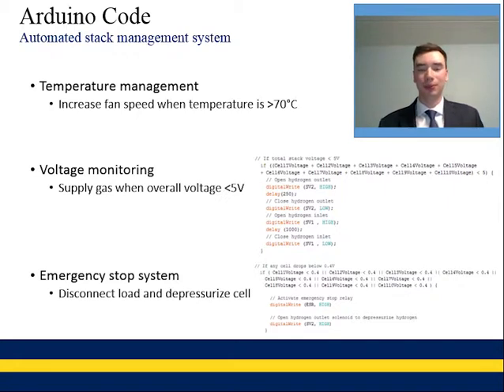So some sub-programs that we have in here: we have temperature management, where if the cells get above 70 degrees Celsius, we're going to increase the pulse width modulation duty cycle to 100%. It's normally going to be around 50% to keep overall power consumption down. But if the temperature gets too high, we're going to have to increase the fan speed to provide more cooling. We also have a voltage monitoring system: when the hydrogen gas gets used up, the overall voltage is going to drop across all the cells. So when it gets below our set 5 volts, we're going to depressurize the cells, which is going to let out mainly nitrogen because the hydrogen is going to be used up. And then we're going to let more hydrogen gas in and repressurize the cell and increase the voltage.